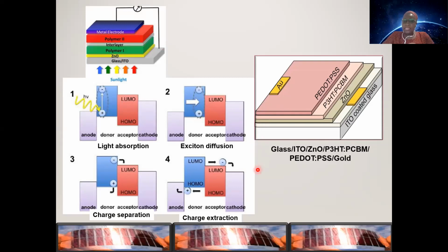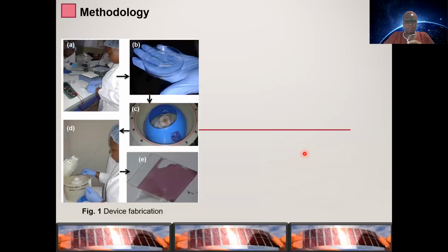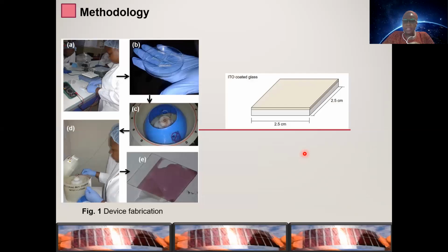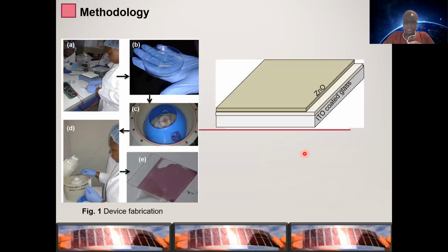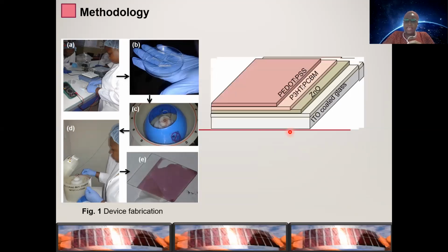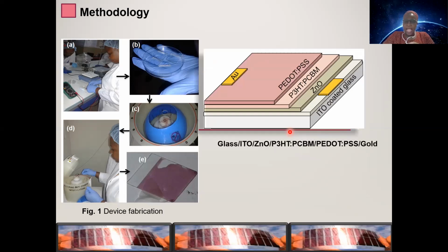And the hypothesis in the study is that we were going to introduce this layer, hoping that when we introduce this heat reflecting agent layer, it will enhance light absorption, which will automatically translate to improving the power conversion efficiency of the device. So our method was that we built on an ITO coated glass. We incorporated the heat reflecting material and then the polymers and a metal electrode. And this is the structure of the device that was built.